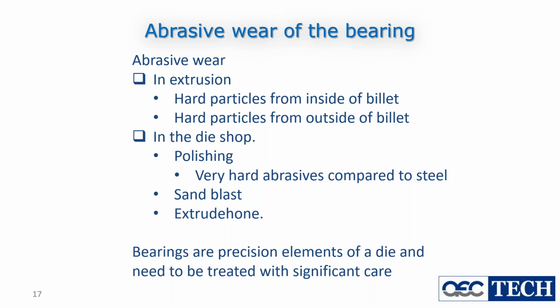So I've seen a lot of die bearing damage done by road dirt and pieces of concrete. The particles inside the billet, if the billet has been properly homogenized, tend to be much smaller and have a much lower chance of doing any damage to the bearing. It's the bigger chunks of stuff that are the problem. But the main source of abrasive wear in the die is when it gets to the die shop. When it comes out of caustic, it needs cleaning because there's a residue, and people polish these die bearings.